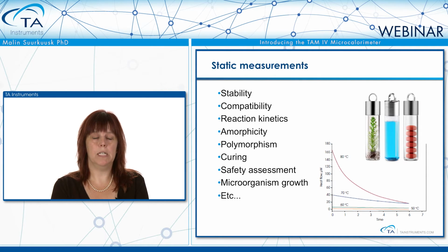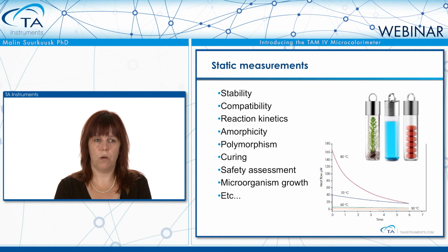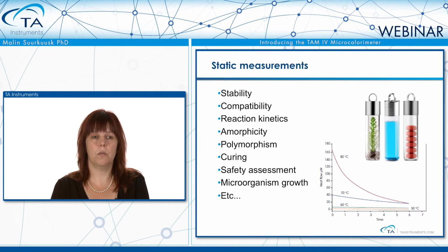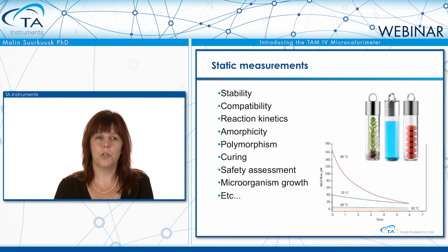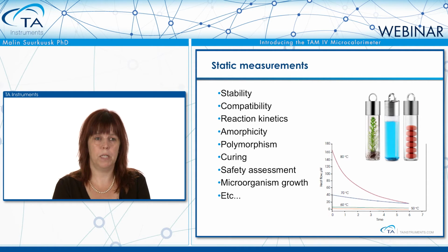The example shown here is a stability measurement where they have increased the temperature of the same sample at different measurements. So we start at 50 degrees. We can see that the heat flow signal is very flat, but it's still offset from the baseline, which means that we are measuring a very slow reaction. By increasing the temperature, we are increasing the reaction rate. So 60 degrees, still flat, but a little higher, so there is more reaction going on. At 70 and 80, we also get curvature because now the reaction is so fast that we're actually consuming sample during the course of the measurement.